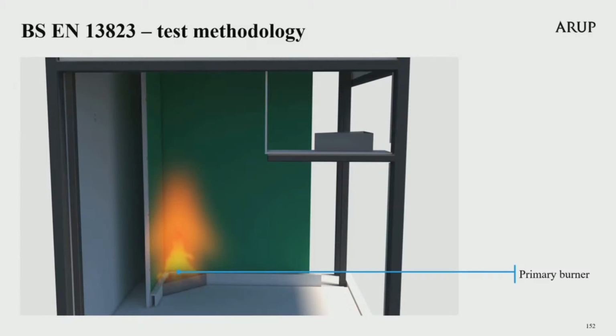Although the burner is offset from the front face, flames given off by the burner can make direct contact with the outside face of the test material. The auxiliary burner is located remote from the test apparatus on a post opposite to the specimen corner and at a height of 1.45 metres from the floor. The auxiliary burner is ignited with the same propane gas supply as the primary burner, but simply to provide a baseline average burner heat and smoke output at the start of the test. In order to subtract the contribution of the primary burner from the measured results at the end of the test, and to carry out calculations with the results and attribute them only to the specimen, the only purpose of the auxiliary burner is to run it for a period of 180 seconds before the primary burner is ignited, and then subtract those values from the total heat and smoke output of the burner and specimen at the end of the main test.